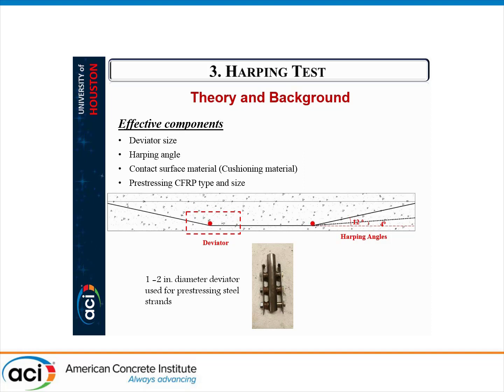knowledge about this topic. So the effective components identified are the deviator size, which in the case of prestressing with steel is usually 1 or 2 inch. And we have the harping angle, which in the case of pre-tension bridge girders varies between 4 to 12 degrees. And the contact surface material and the type and size of the prestressed CFRP can be other effective components for harping.